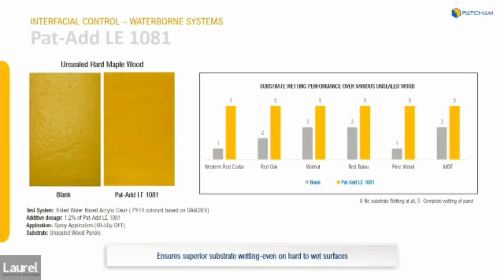So what happens to the stabilization mechanism during that time? Fortunately for the formulator, he only has to prevent the flocculation of the system until the film is no longer mobile to reflocculate. Once it can't move anymore, who cares? But that's the challenge: take that waterborne coating as it becomes less and less waterborne and resist the physics, because physics says it's going to flocculate. And we say, no, we're going to keep it from flocculating, but only till the coating is no longer mobile enough to flocculate. So the sealing over variable substrates, the wetting out, the uniform wetting out of a waterborne coating system.